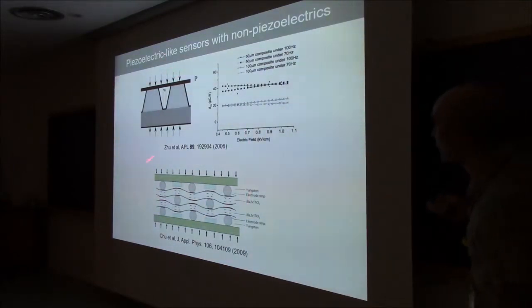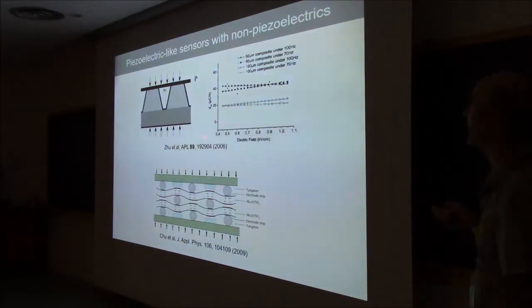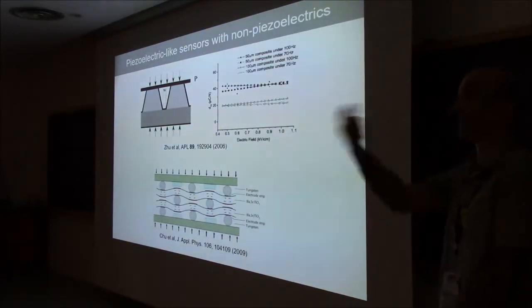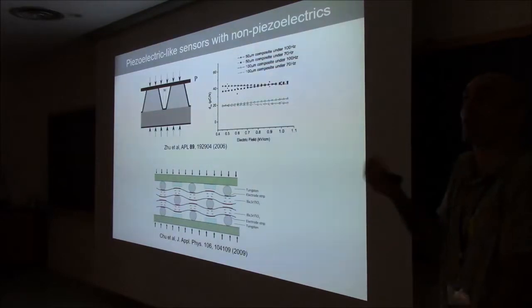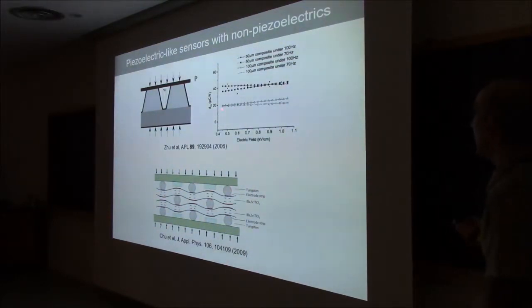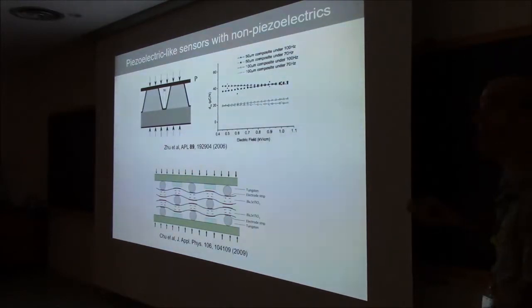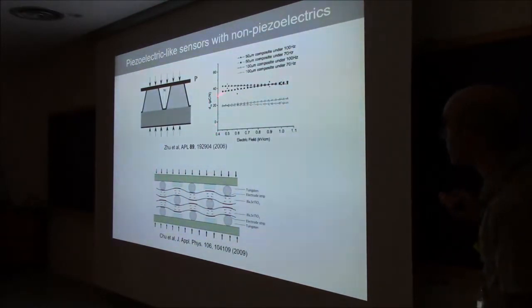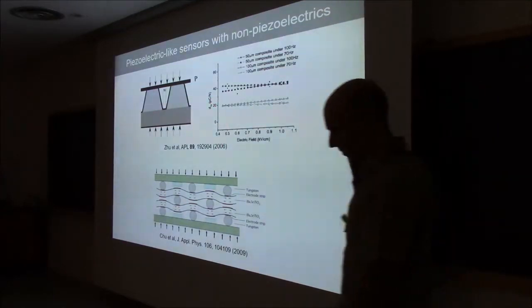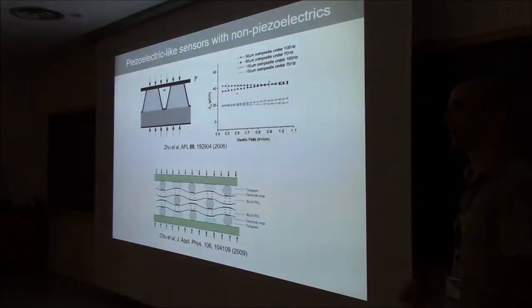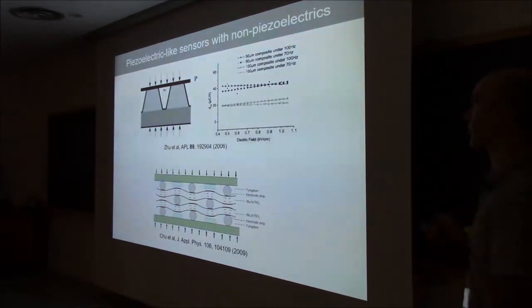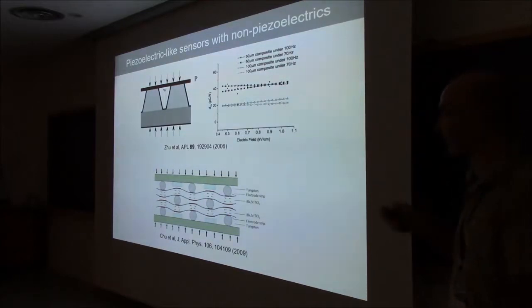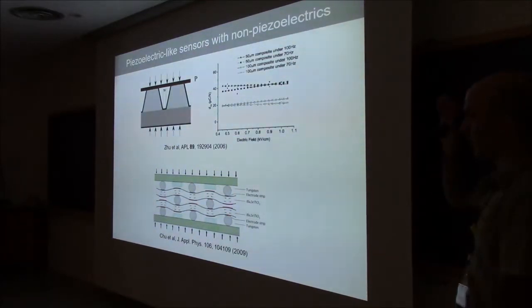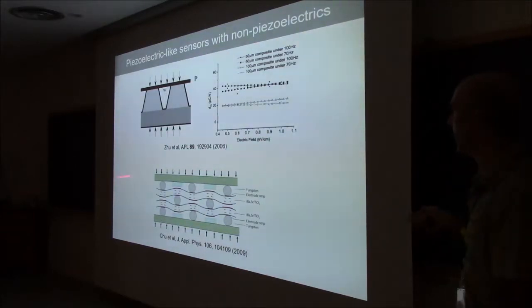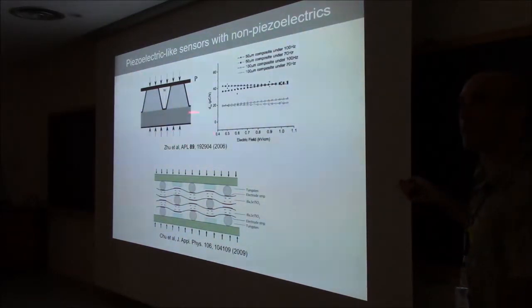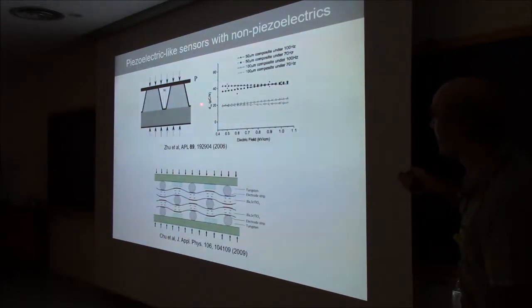So I apply a force to my asymmetric truncated pyramid, and I measure a polarization, and if I divide that polarization by the force, that is the definition of the effective piezoelectric coefficient. And you can measure it. That was done by the group of Eric Cross at Penn State, and they saw that it was sizable. They did this experiment with barium strontium titanate in the paraelectric phase, paraelectric but still with some parasitic piezoelectric contributions, and that's why it has such an enormous flexoelectric coefficient. But that's irrelevant. The point is, he used a material that is non-piezoelectric, shaped it like so, and compressed it and measured an effective piezoelectric coefficient.